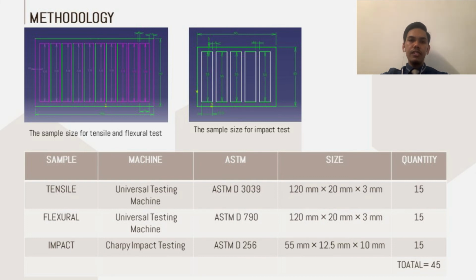Next, for flexural samples, we also use a universal testing machine in accordance with ASTM D790, with 120 mm length, 20 mm width and 3 mm thickness. Also, we will produce 15 pieces for those 3 ratios. And finally, for impact samples, we will use a Charpy impact test in accordance with ASTM D256, with 55 mm length, 12.5 mm width and 10 mm thickness. The samples for those 3 ratios will be 15 samples. The total will be 45 sample pieces.